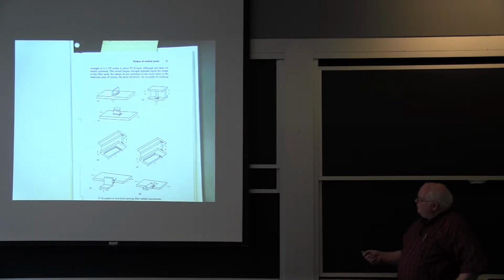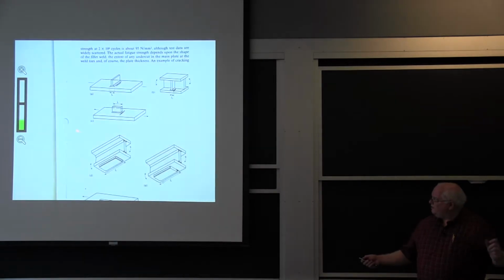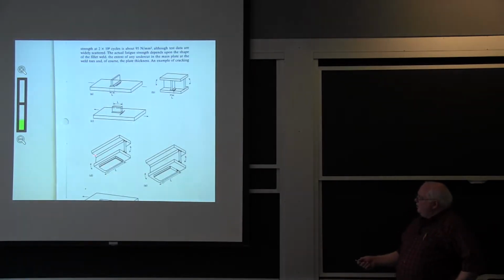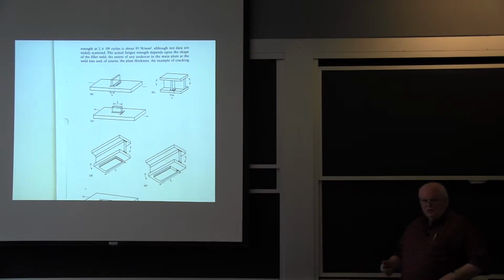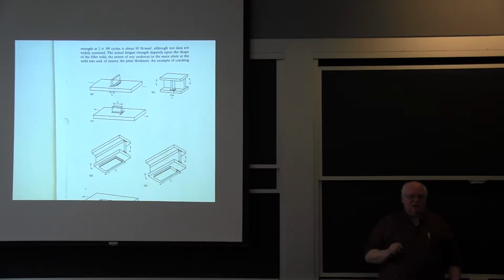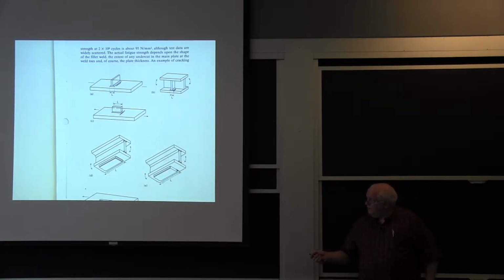But if you look very carefully, right at the end of this one, there's a little fatigue crack. Right here at the toe of that one, there's a fatigue crack they're trying to show. Here's a fatigue crack. Every one of these ends up becoming a location for a fatigue crack. And in fact, this type of detail right here, where they weld the end of a doubler plate on to stiffen up the beam or for whatever, that's the reason for the King Street Bridge failure in Australia, which is sort of a famous weld failure.